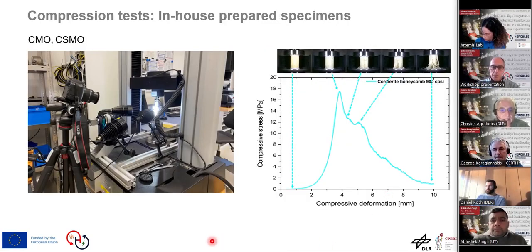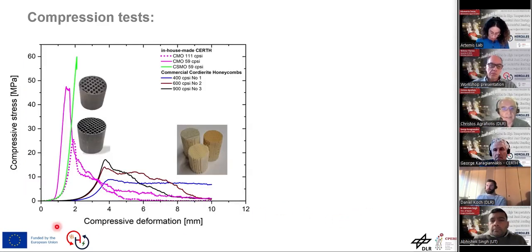These rigid specimens after the calcination, we go to the next slide and we see, for instance, tests with respect to their mechanical strength. We do crushing strength of this kind of specimens, and we also can record and identify where the material fractures, let's say, along the stress strain curve, as you can see there with successive photographs. Next slide shows quantitative results of such comparisons.